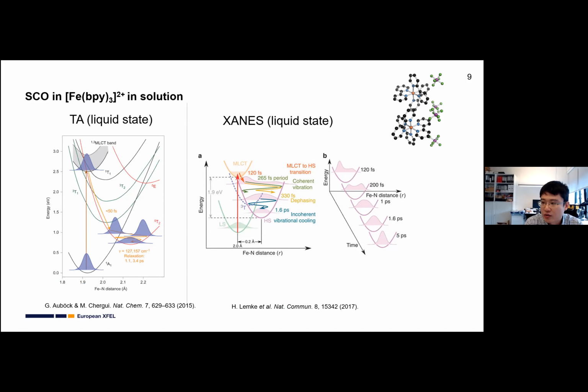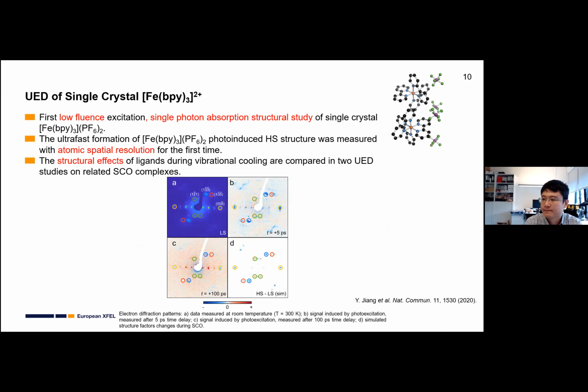We can either use X-ray diffraction or electron diffraction, and we use electron diffraction to study it in this work. So it's also important to mention it's a very low excitation, single photon absorption structure study, because electron diffraction is very, very sensitive to sample damage. So even a little bit of damage, we can notice easily. So we use very low excitation. We only pump 10% of the overall molecules, so 10% excitation fraction.